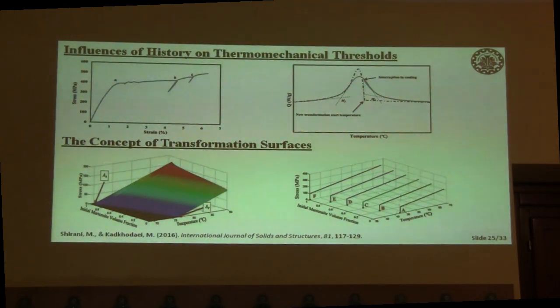Even in DSC, in the course of heating and cooling, if I interrupt the heating during transformation, meaning partial transformation, and revert the heating or cooling cycle, I would obtain a different value of transformation temperature. This means transformation temperatures are a fixed number only if I induce complete transformation. During cyclic loadings, I may face some partial transformation. Therefore, I should develop a model to predict the changed value of transformation temperatures in the course of incomplete transformations.